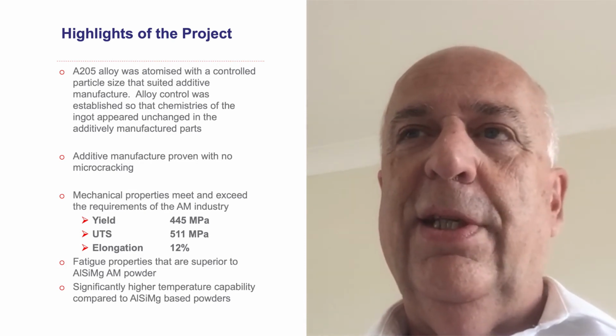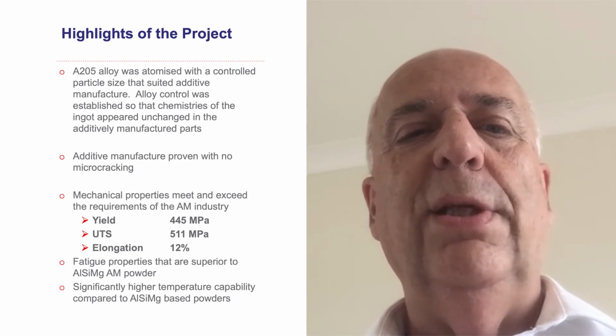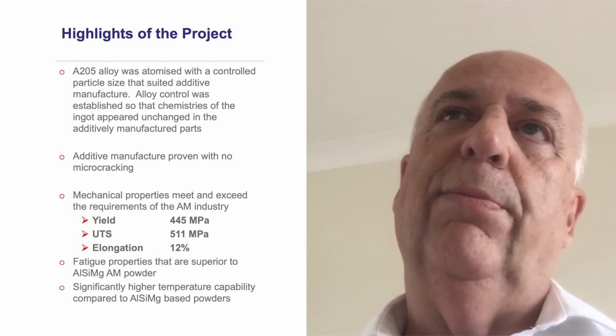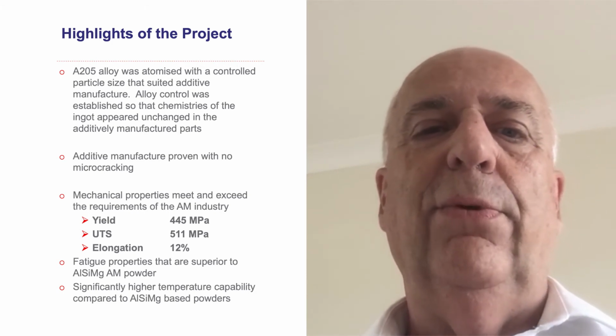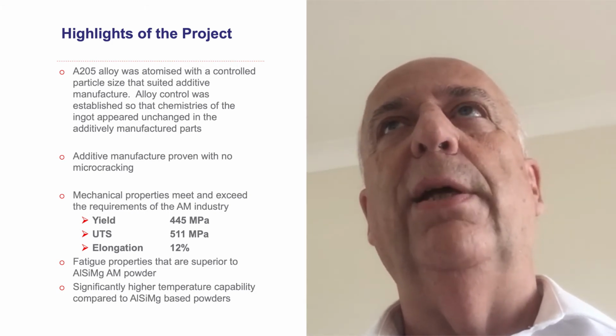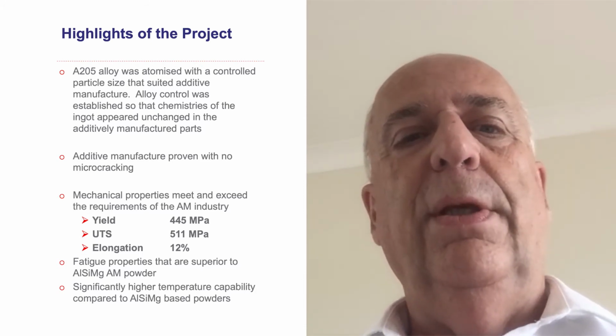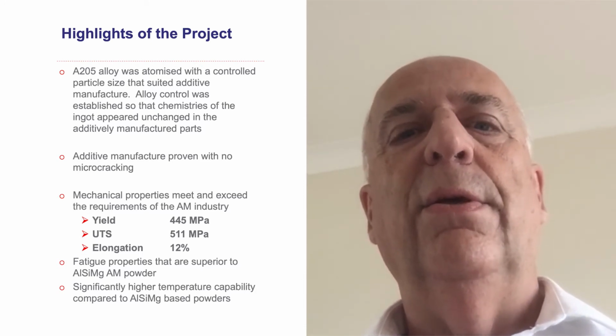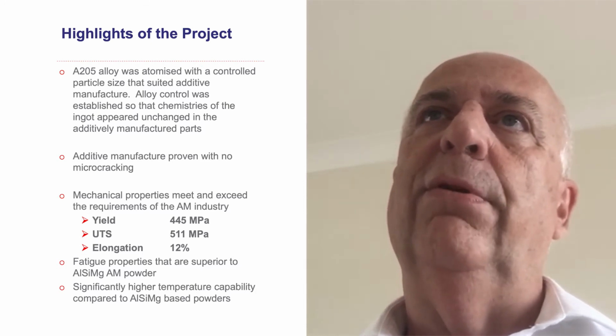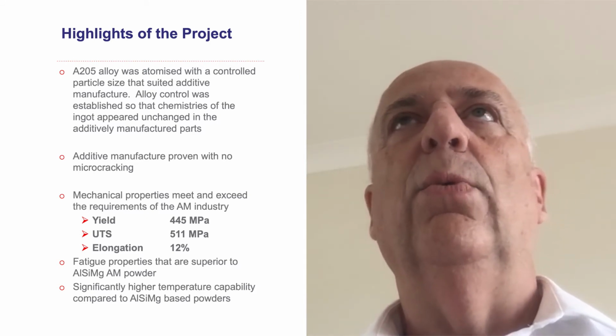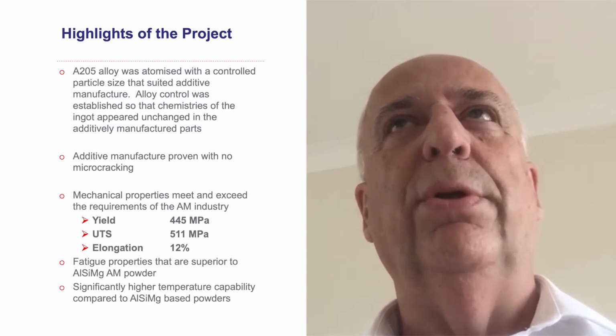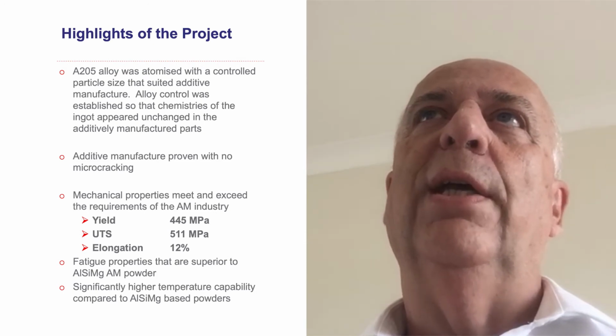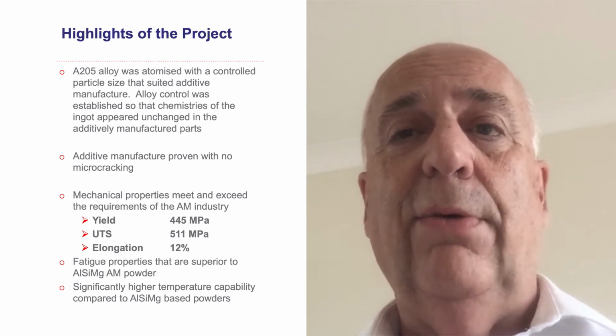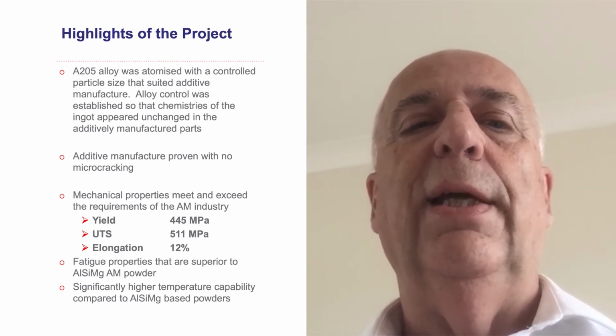For the metallurgist, I'll give you the details. The yield point, that's the point at which it becomes plastically deformed, was 445 megapascals. The ultimate tensile strength was over 500 at 511 megapascals. We in fact achieved higher than that within the project, but that was done with a change of chemistry, which is too detailed for this short talk today.